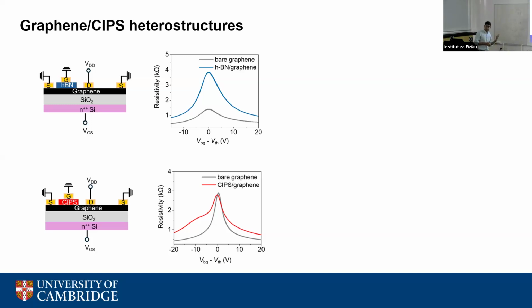We are very scared to call it a Dirac peak because we don't have evidence to call it. We don't want to call it a second Dirac peak right now, but we see a resistivity peak. But why do we have this peak? How can we correlate this with the properties of CIPS? As I said, CIPS is an ionic conductor as well. It has copper ions. And people have shown that if you increase temperature, the motion of these copper ions in this material changes. So we did temperature dependence of this resistivity.